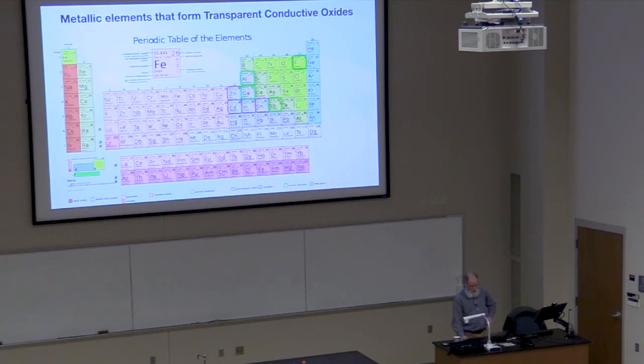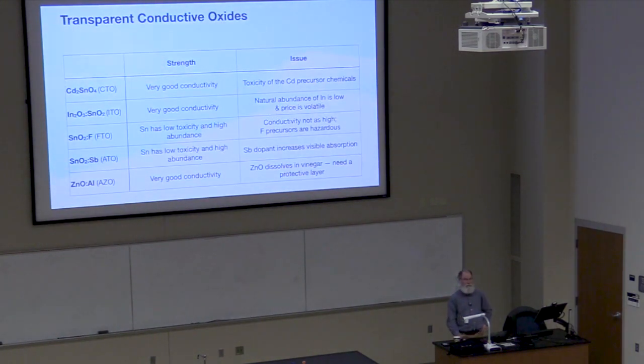To make it really conductive, you need to dope it with other things. So these elements are used to dope these elements. For instance, if you make zinc oxide on its own, it's not a great conductor. But if you dope it with something adjacent to it, gallium, or aluminum, it's a good conductor. You can make tin oxide with antimony in it, tin oxide with fluorine. You can make indium oxide with tin in it, cadmium oxide with tin in it. So there's only a handful of candidates here, but there are quite a few combinations to look at. So let's look at some of those combinations.